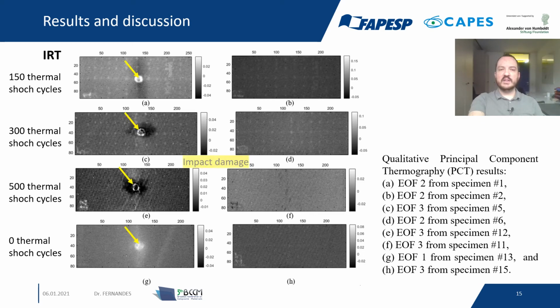We can observe clearly in all images the impact damage, which is also visible with the naked eye, here in the center of the specimen, indicated by the yellow arrow. We can also see, especially in the specimens with the higher number of thermal shock cycles, that delamination around the impact has formed. So there could be interply and intraply debonding here. And also we can see cracks in the specimens. We can also see cracks here in the specimen which was submitted to 500 thermal shock cycles but not impacted.